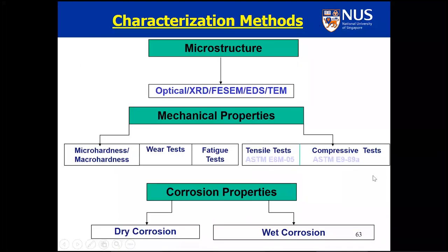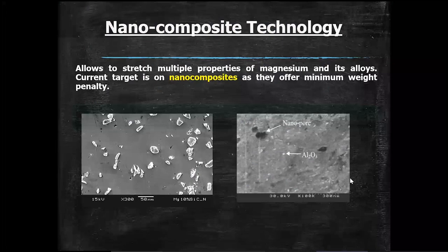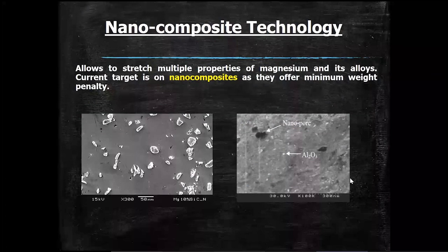Now, all these materials and methods are okay, but the properties should be good. Otherwise, there is no point. So one of the materials that we have focused on for quite some time is the development of nanocomposites, besides the conventional alloys. The nanocomposite is very simple. You can either convert the matrix grain size into the nano length scale, or you just reduce the reinforcement size to the nano length scale. Either way, it is called a nanocomposite. We use the approach of reducing the size of the reinforcement to the nano length scale. What you see in the picture on your right-hand side are small Al2O3 particles of about 50 nanometer size, and the big particles you see on the left-hand side.